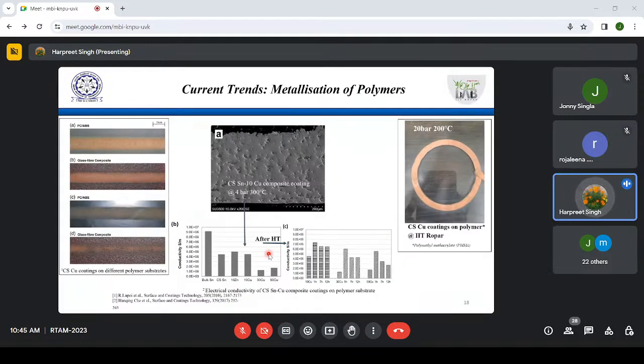So this is about metallization of polymers, right? You can see some polymer coatings have been deposited. These are all glass fiber composite, PC, ABS, and we also do copper coating on the PMMA substrate, right? At IIT Ropar, this pure copper coating could be deposited on this PMMA sheet and so on. Copper coating on different polymer substrates has been produced, right? So these all have nice applications in several domains.